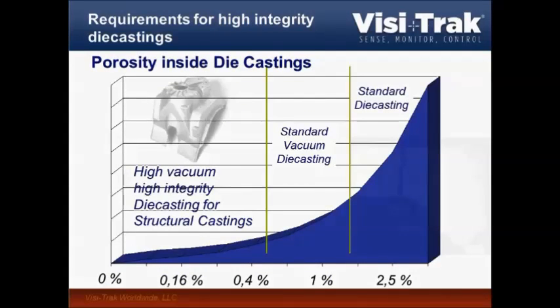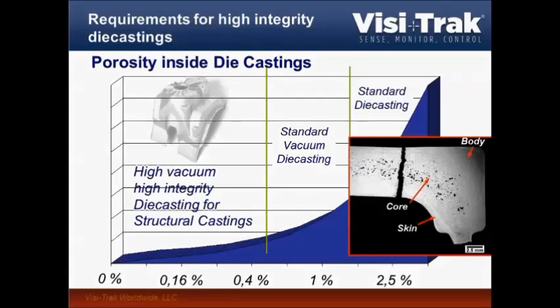So standard die castings are sometimes described as two sound skins around foam. And when we look at this part, whenever it gets too thick, we always run into this problem, that we get all sorts of porosity inside, while the skin is actually perfectly sound, and even the body is pretty good. Therefore, what we want to apply is vacuum, and not just standard vacuum, but really high vacuum. And it's of course not just about the vacuum, it's also about doing, as mentioned before, everything else right.